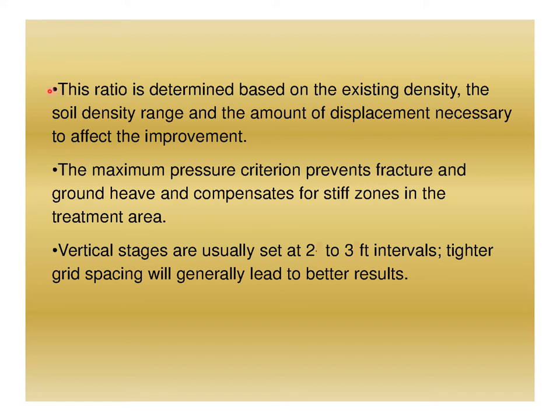The replacement ratio is determined based on existing density, the soil density range, and the amount of displacement necessary to achieve improvement. The maximum pressure criterion prevents fracture and ground heave and compensates for stiff zones in the treatment area. Vertical stages are usually set at two to three feet intervals; tighter grid spacing will generally lead to better results.